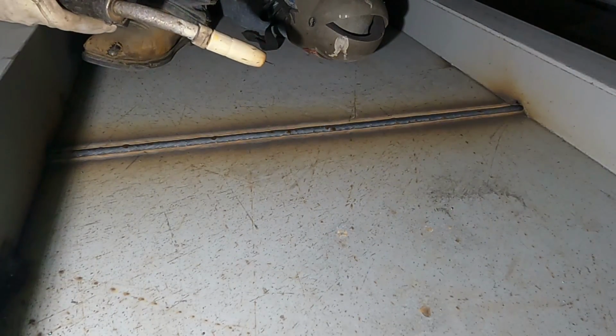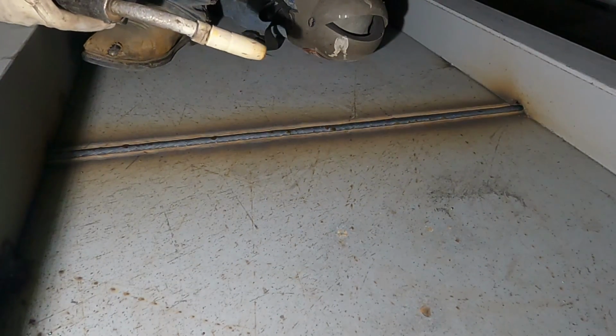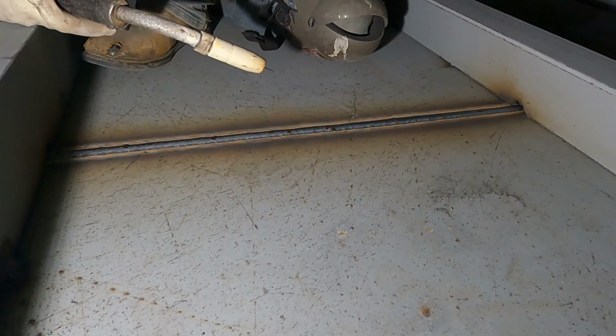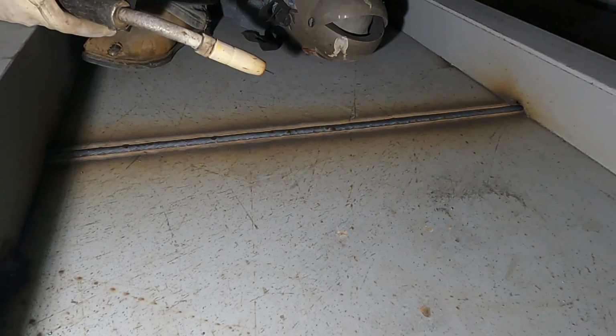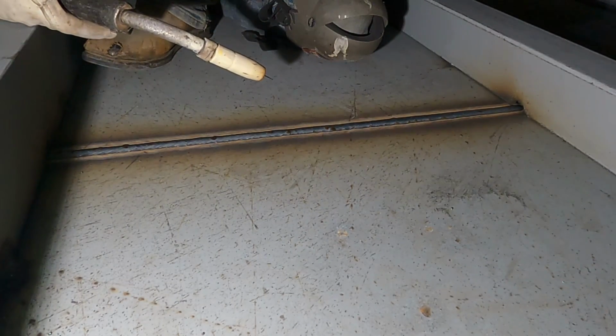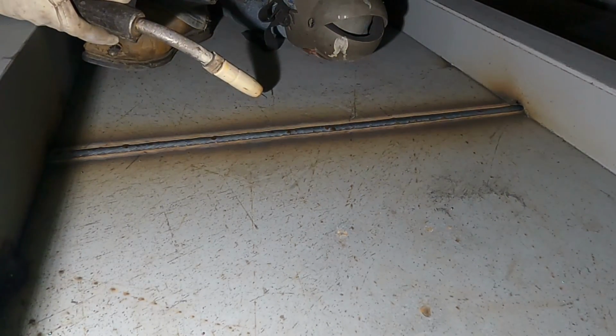Anything longer than that with this GMAW, you'll get porosity real easy. It's real sensitive because it's not dual shielded. So you get porosity real easy from wind, moisture, any kind of contaminants like that. So you want to make sure you're keeping your material clean and a nice tight arc length. These settings will be good for just good quality, good production.